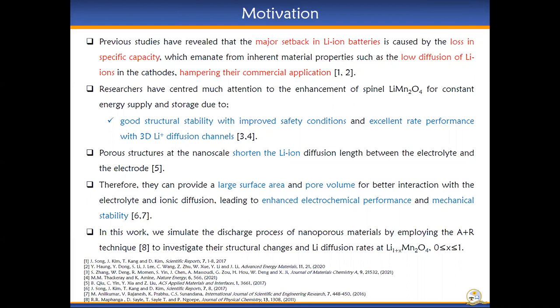Porous structures at the nanoscale shorten the lithium ion diffusion length between the electrolyte and the electrode. Therefore, they can provide a large surface area and pore volume for better interaction with the electrolyte and ionic diffusion, leading to enhanced electrochemical performance and mechanical stability. In this work, we simulate the discharge process of nanoporous materials by employing the amorphization and recrystallization technique to investigate their structural changes and lithium diffusion rate at different lithium concentrations.